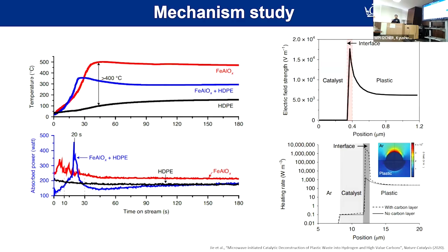So literally, when these two materials interact with the microwave, they will generate very high surface electric fields. Although we cannot quantify the contribution of the formation of these surface electric fields to the catalysis, it does tell us we need to pay particular attention to what happens at the interface between the catalyst and the feedstock, or even in the catalyst itself.